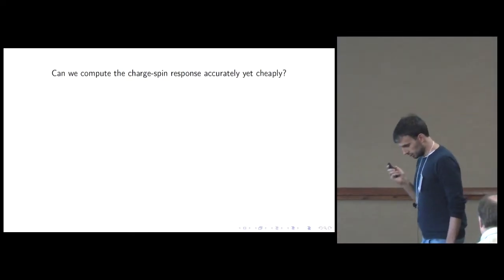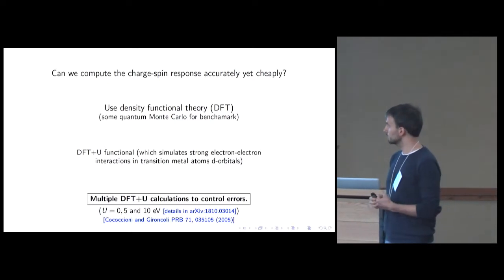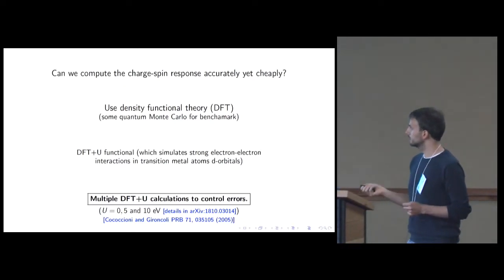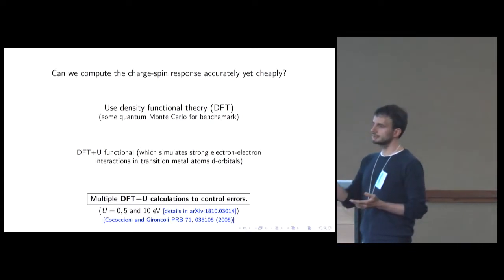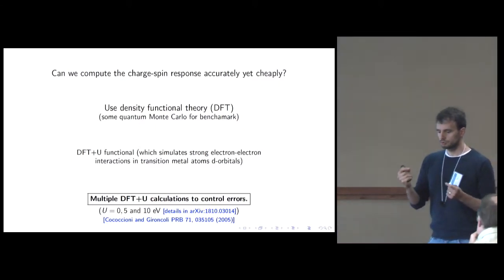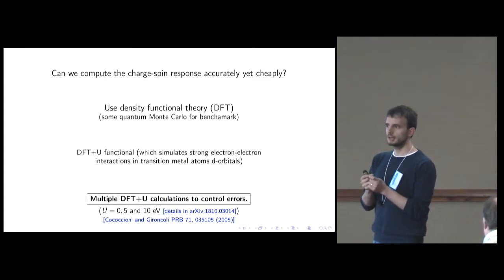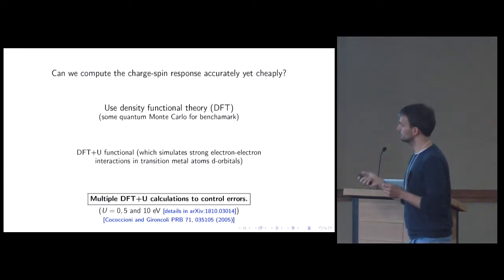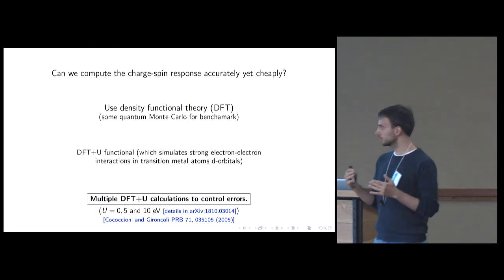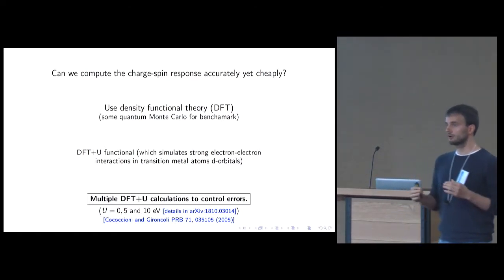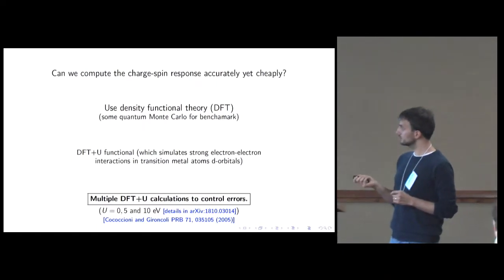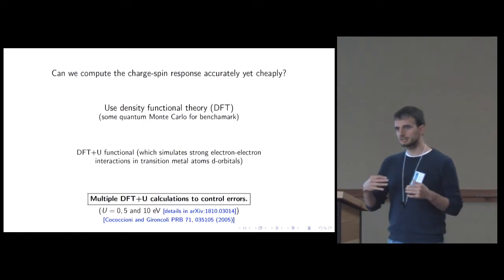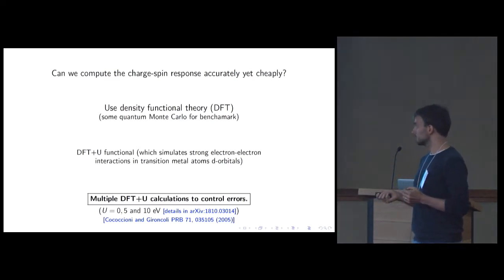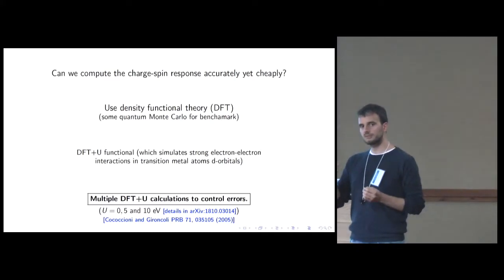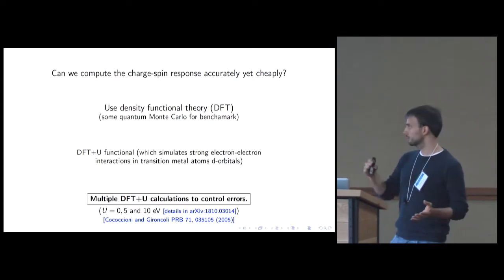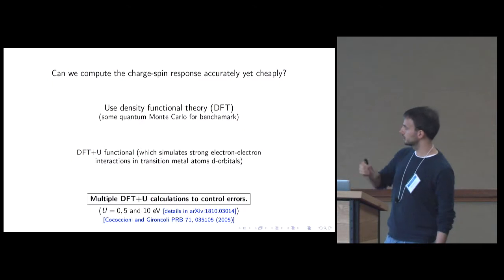In order to compute this quantity, we essentially use density functional theory. We use the DFT plus U functional. That is a functional that assigns a larger interaction whenever two electrons are sitting on transition metal atoms. That should be so because we know that electrons interact much more in transition metal atoms, because these have open shell d orbitals. And the issue is that this U stands for the strength of this interaction, and we don't really know its value. So in the end, to control errors, we do several values of U to try to bound the errors from below and from above, from excessive U or defective U.